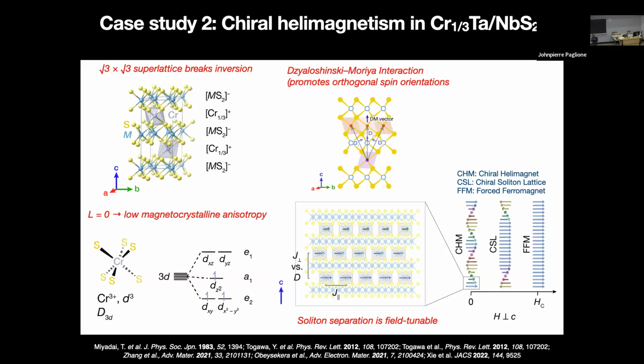And then as you apply a magnetic field within the plane of that crystal, you can start to unwind this helimagnet into these chiral soliton lattices until at some critical field you end up with basically a forced ferromagnetic state where you've overridden the DM interaction, and you've forced everything to be aligned with the magnetic field. Okay, so this is a pretty interesting class of materials that was, I think, some of the first reports were from Miyadai in 1983, or maybe even there was some work before that.